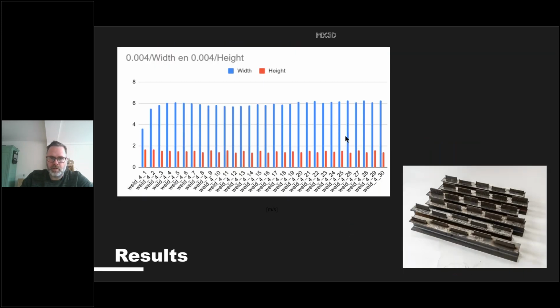So here you can see a typical result of a scanning of a complete wall per layer. The blue lines are the wall width, and the red lines are the wall height. And you can clearly see that for the first couple of layers, the layer width is less because it's printed closer to the substrate, and the cooling, the solidification, is much quicker.